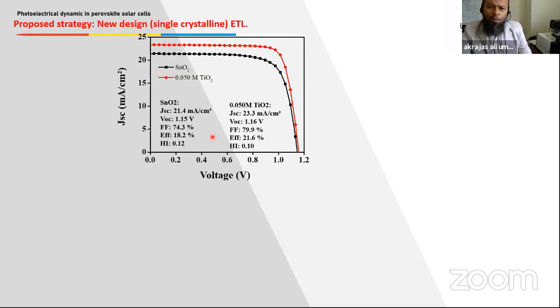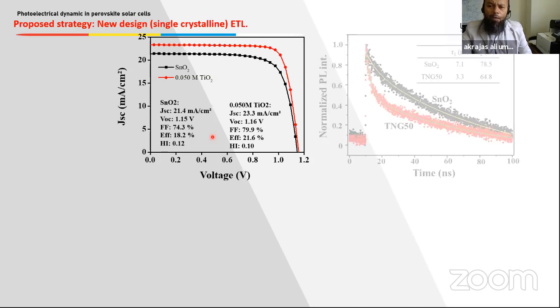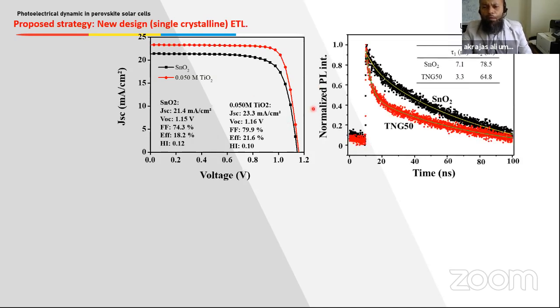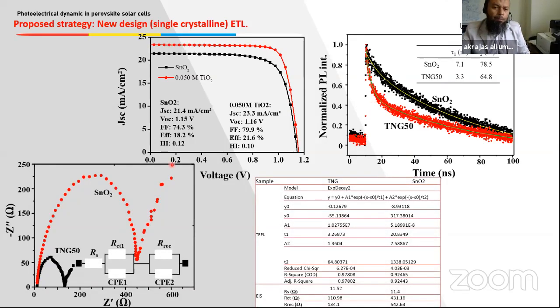So we look at the nature of charge transfer at the interface by doing transient photoluminescence spectroscopy. We try to describe and compare the nature of charge transfer between these two systems. This is a typical photoluminescence quenching profile. We fit this result with an exponential decay function, and from this function we got two time constants, namely a fast time constant and a slow time constant. The fast decay time constant is associated with the interfacial charge transfer dynamic. We can see here that the interfacial charge transfer dynamic in the nanograss-based device is much faster than in the SnO2-based device.